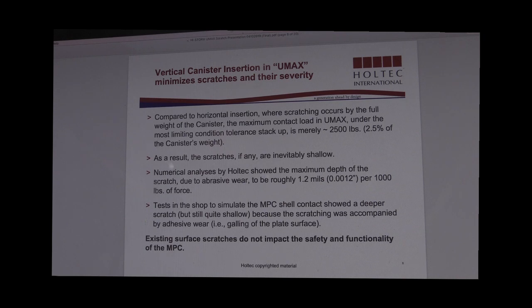Whereas in a horizontal system, that lateral contact load on the shell could be much more significant, as much as the full weight of the canister system. So this limits the potential size and depth of the scratches, and our own investigation, both numerical and through tests, show that those scratches are shallow with respect to the thickness of the shell. And in fact, our estimates of the abrasive wear